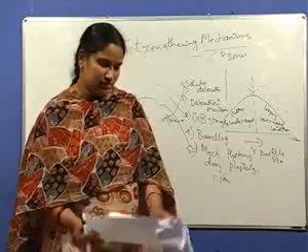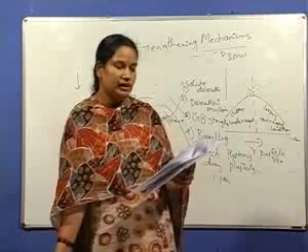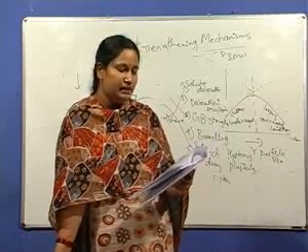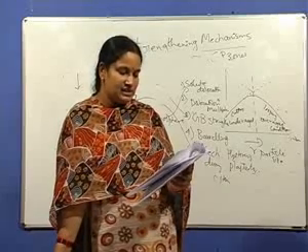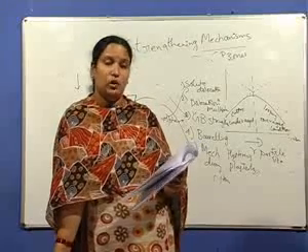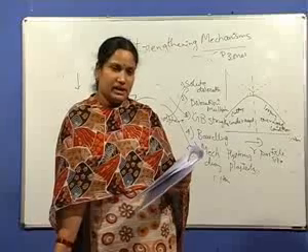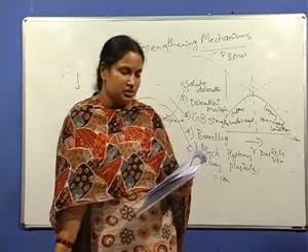And one more question, that is question number 34. Stacking fault energy plays an important role in determining the work hardening ability of a metal. In this context, the correct logical sequence is: A, high stacking fault energy, easy cross slip, low work hardening. This is the first option given.